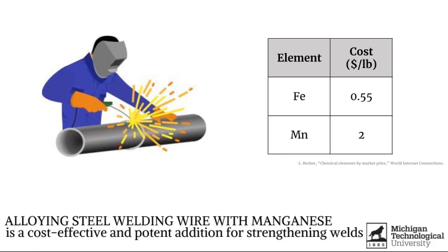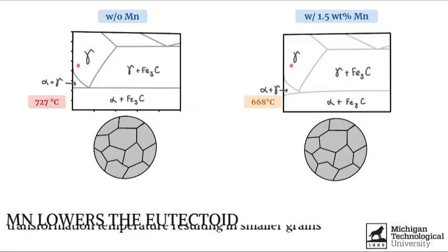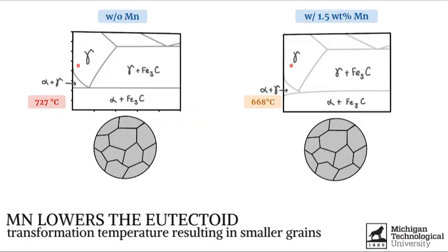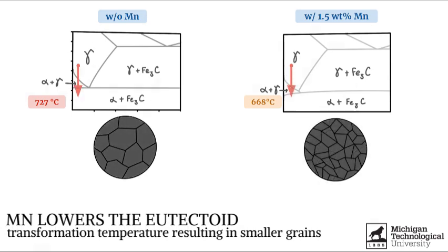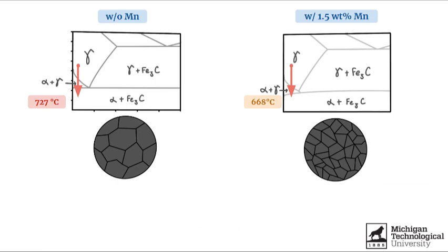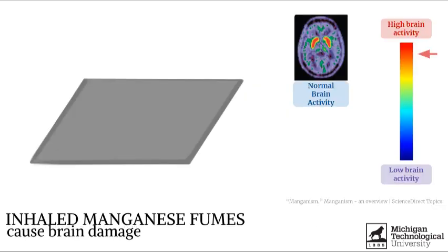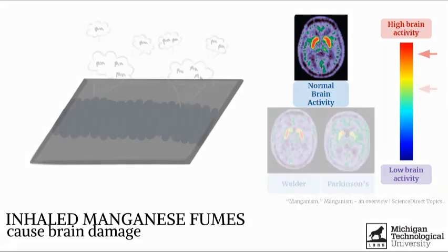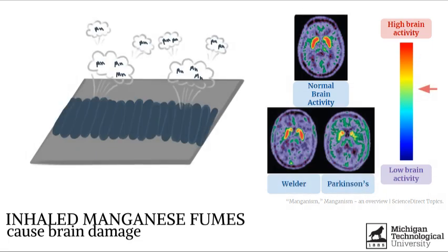Manganese is commonly added to the wire because it is a potent addition for strengthening welds and is also cost-effective. The reason manganese is effective at strengthening is because manganese lowers the eutectoid transformation temperature, which allows for more nucleation during cooling, resulting in a smaller grain size. Despite these advantages, manganese is a big health concern because during the welding process, manganese fumes are produced, and these inhaled fumes can cause brain damage similar to Parkinson's disease.